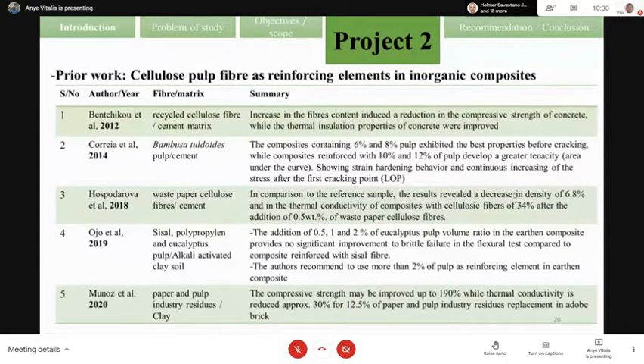Hospodarova used recycled waste paper in the cement mortar, and realized that by introducing that cellulose fiber in the cement, they reduced the density and the thermal conductivity of the cement mortar. Later, Ojo et al. studied polypropylene and eucalyptus pulp, and realized that by using 0.5 to 2% of the cellulose fiber, there is no significant improvement in the type of the brittle failure of the material, and suggested using more than 2% of cellulose pulp to have a significant improvement of the reinforcement efficiency.